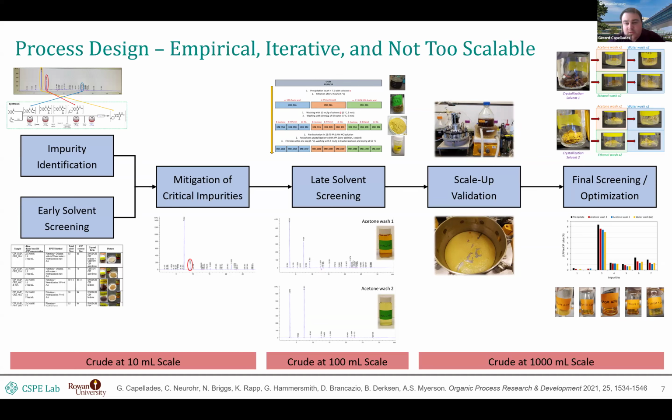And you don't know if that impurity ended up like that because it was, let's say, supersaturated, but with a long induction time in your experiment, and therefore it never precipitated at the smaller scale, right? And then you're now scaling things up, and suddenly that impurity is able to crystallize because it has a much shorter induction time, and suddenly the impurity that was not showing up in your early process development is now appearing, right? Or there could be additional mechanisms by which the impurity may end up inside the crystal lattice, right?